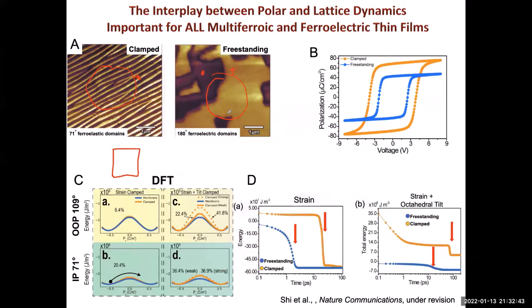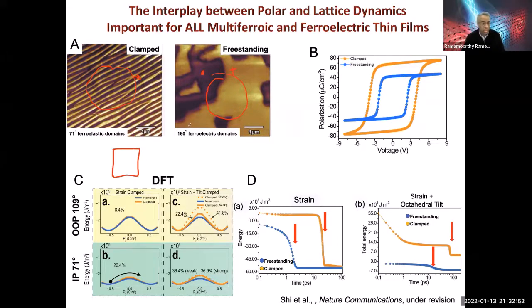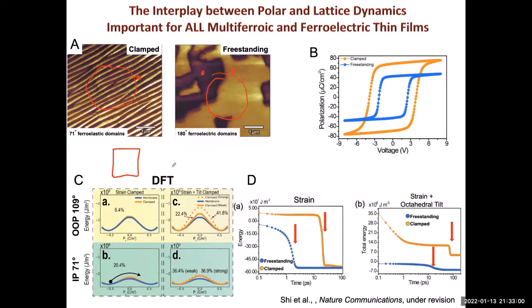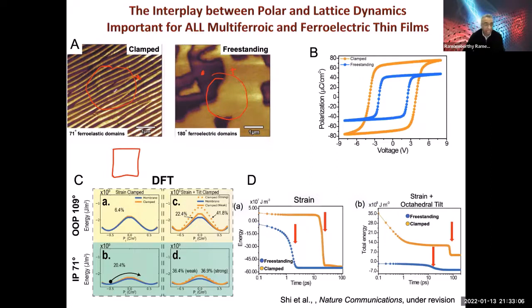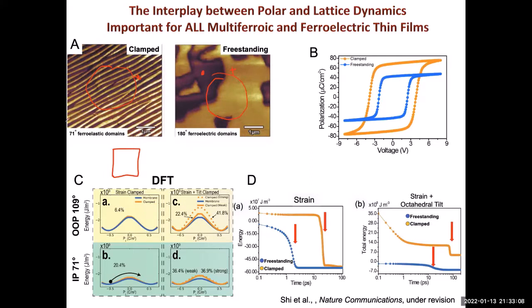Kind of, but I was just wondering how much strain are you talking about in this case? Oh, I see. That's a good question. The mismatch strain between the substrate and the BFO is of the order of 0.7%. That's not huge. Oh, I see. So even for such a small strain percentage, because of the shape of the unit cell, you're saying that it induces such a different behavior. Oh, very nice. That's right.